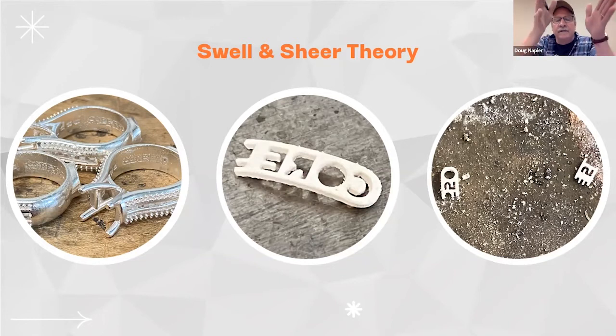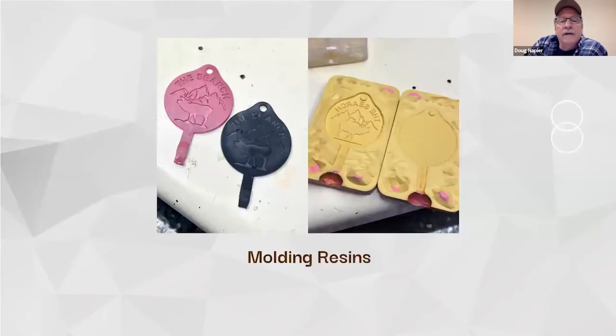So one of the things I like to do, especially in lettering, is taper everything so that you don't have just straight up and down, but just a little bit of a taper so that the base of that investment is supported a little bit more. Control your depth, figure out what's the narrowest I can get by and still look good. And then, if possible, go ahead and fillet your edges, and that'll add a little bit more strength to your investment as well. And again, with the stone settings, evaluate them: do they need a thin through hole? Can you get by with a thicker through hole, or can you get by with a divot with no through hole? And then once you get it in metal, go ahead and drill them out that way.